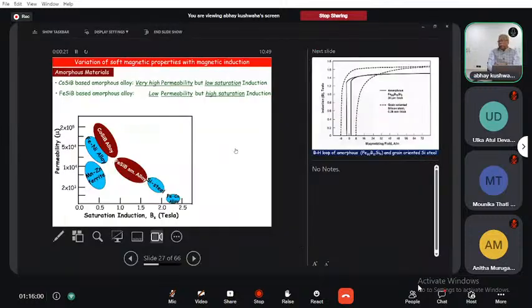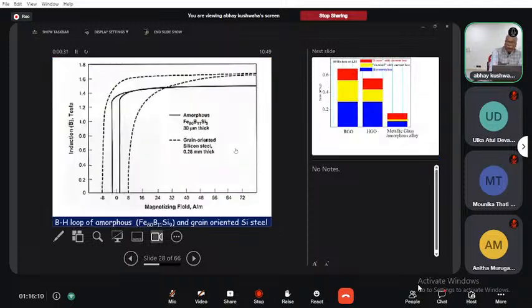Iron, silicon, boron, these are the type of materials. Now, if we consider this material and compare it with the hysteresis loop of the silicon steel, you can easily see that amorphous iron, boron, and silicon has a very narrow loop as compared to the grain-oriented silicon steel. So there is a huge reduction in the hysteresis loss, and at the same time, because of the amorphous structure, the resistivity of this material is quite high as compared to the crystalline structures.